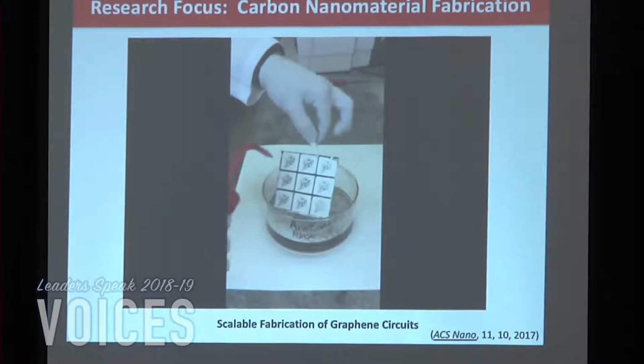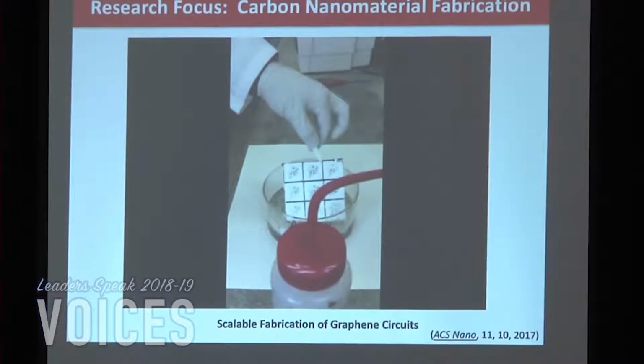What's kind of interesting, this technique that we figured out, is that we're patterning the polymer underneath, just like a photoresist that you use in photolithography. And then we're coating it with graphene. So that acetone has to go through that flake layer, that black flake layer that was on top, hit the polymer underneath, etch off or react with that polymer where it is, and then lift off the graphene that's on top of that. And then wherever that polymer wasn't underneath, the graphene that was on that backing substrate stayed there. So it's a unique little process that we did.